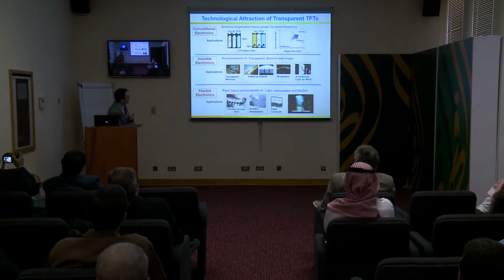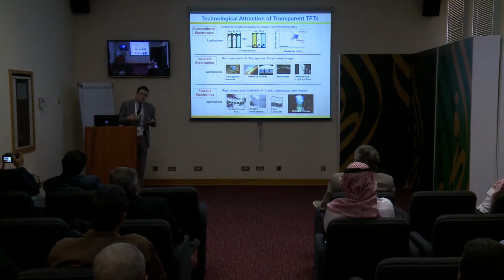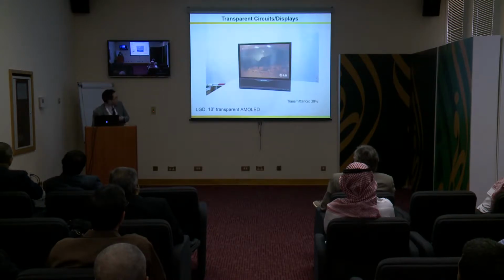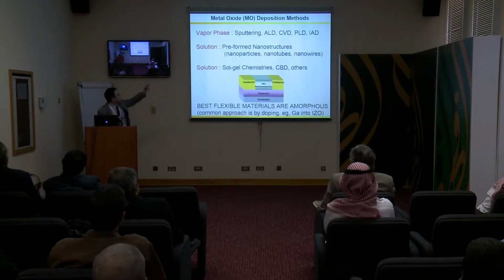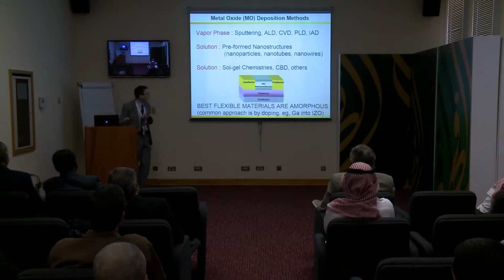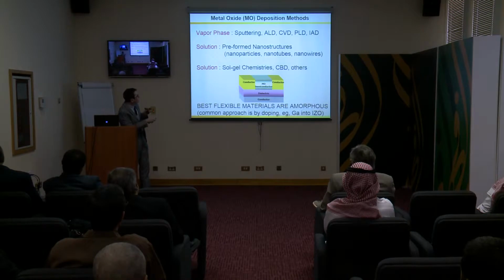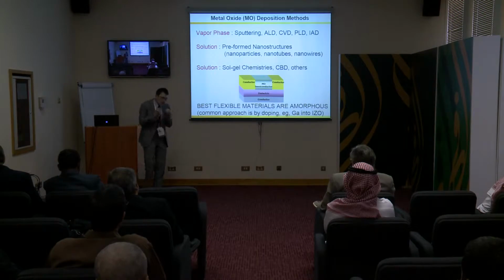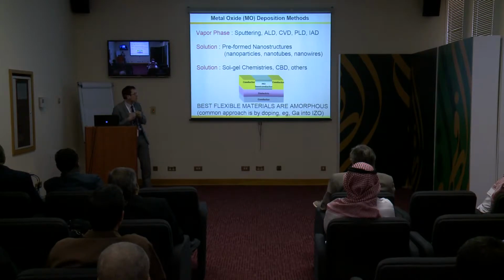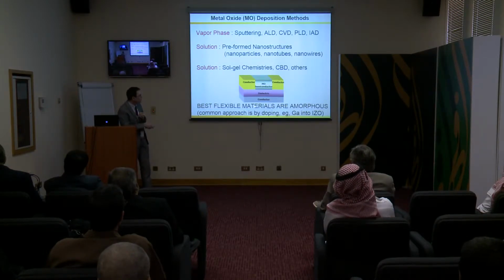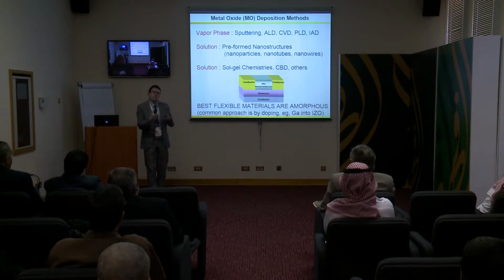The other area is making invisible displays, and a third area is flexible electronics, because these amorphous phases are mechanically tolerant to mechanical stress. So we have done a fair amount of work to deposit metal oxide going from vapor phase, from solution phase using preformed nanostructure, or using Sol-Gel methodology and other methodology. But what is the key importance, especially if you think in the vision of printed electronics and flexible electronics, is you really need to make an amorphous phase. So what is the typical way to make amorphous phase in a metal oxide?